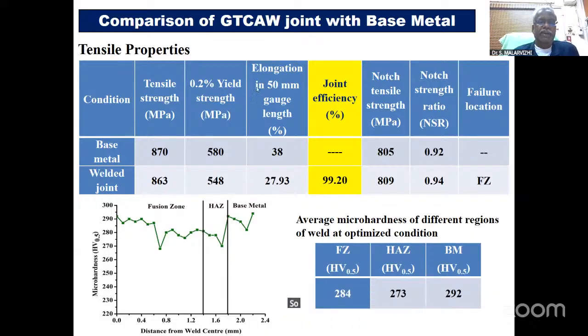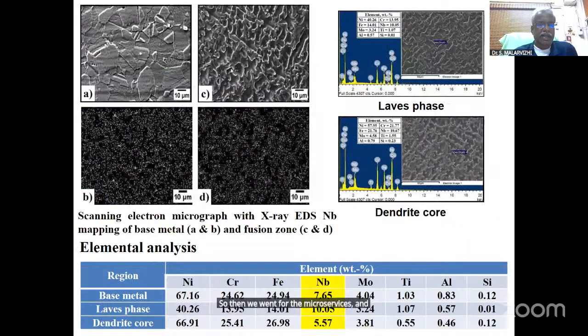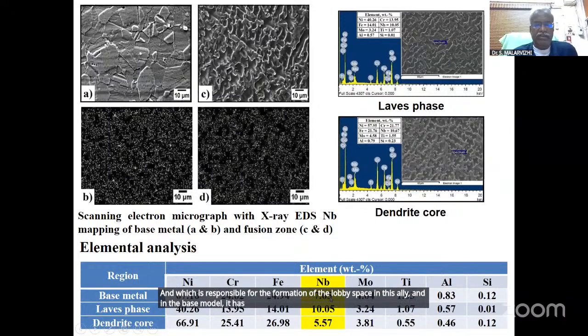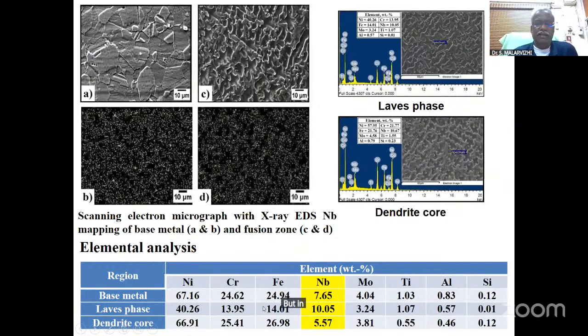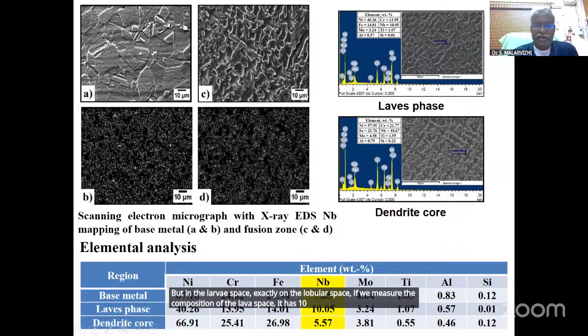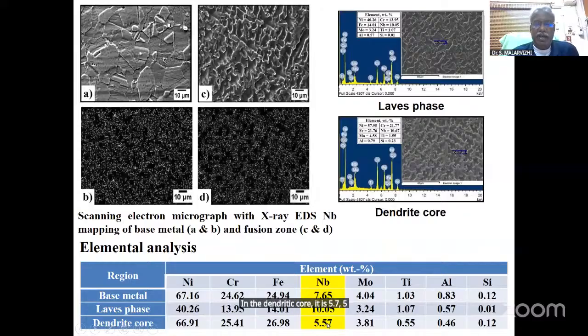Then we went for the microstructure analysis, and the elemental analysis was done. If you see the niobium, which is responsible for the formation of the Laves phase in this alloy, the base metal has niobium of 7.65%. But exactly on the Laves phase, if you measure the composition, it has 10.05% of niobium, nearly a 2.5% increase in the Laves phase. In the dendritic core, the niobium content is 5.57. So how do we minimize the formation of the niobium-rich Laves phase?